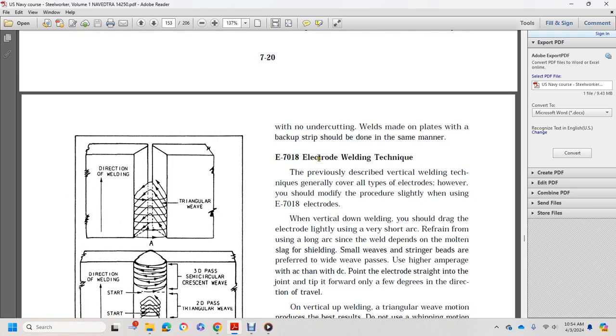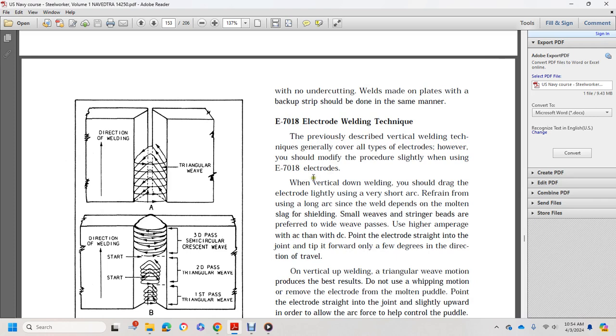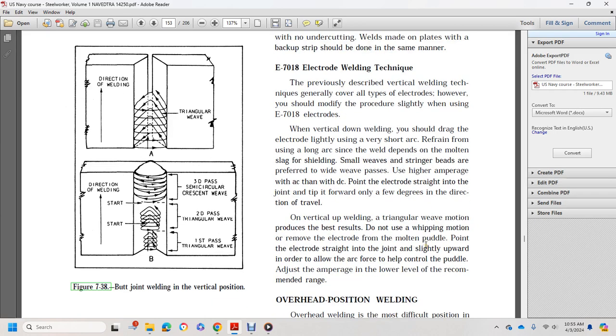The E7018 electrode welding technique, like the previously described vertical welding technique, generally covers all of the types of electrodes. However, you should modify the procedure slightly when using the E7018. For vertical down welding, you should drag the electrode lightly using a very short arc, and refrain from long arcs since the weld depends on molten slag for shielding. Small weave or stringer beads are preferred to wide weave passes, with higher amperage on AC than DC. Point the electrode straight into the joint and tip it forward only a few degrees in the direction of travel.